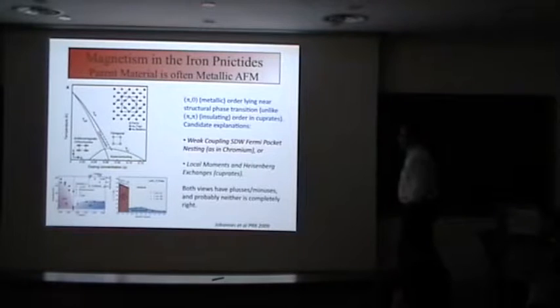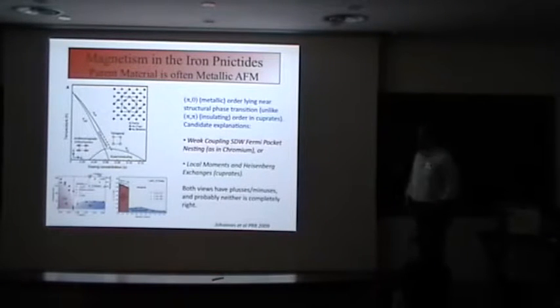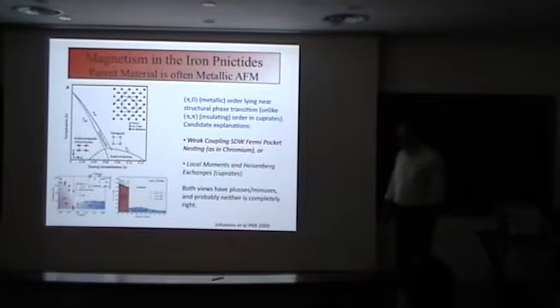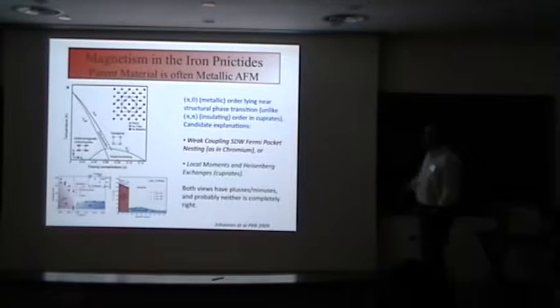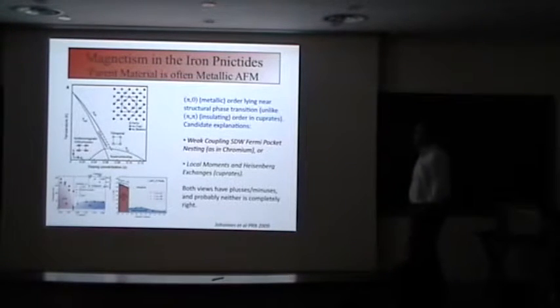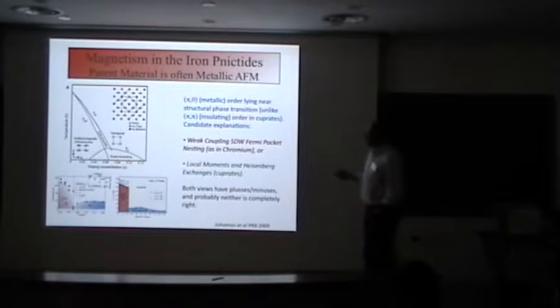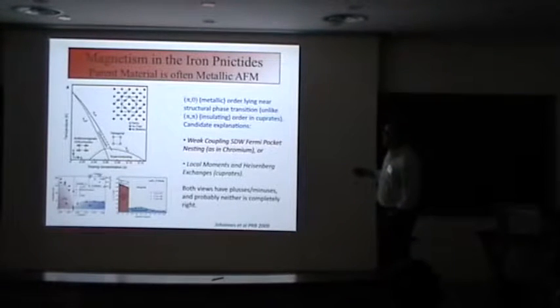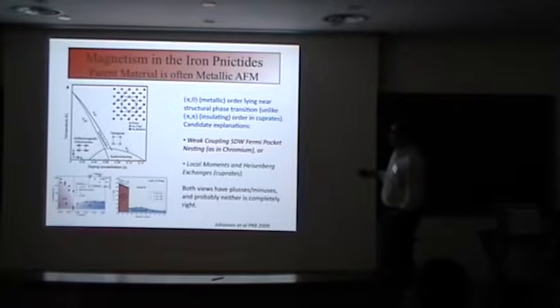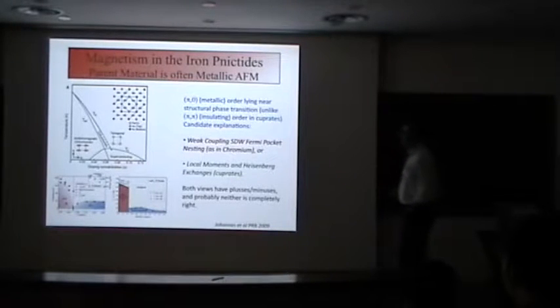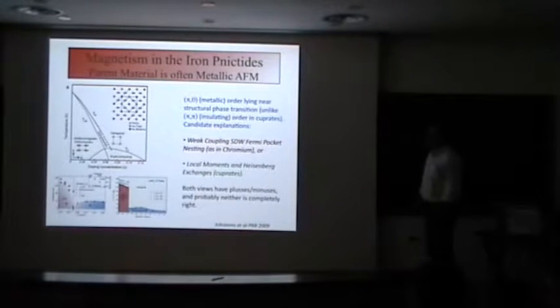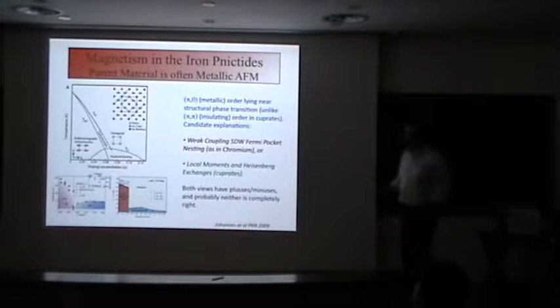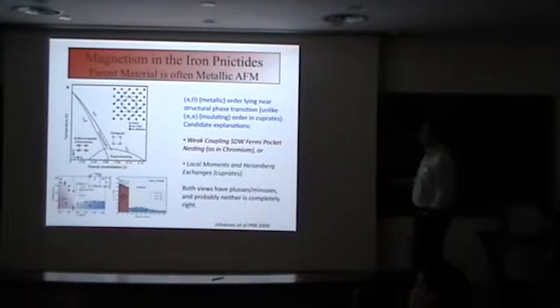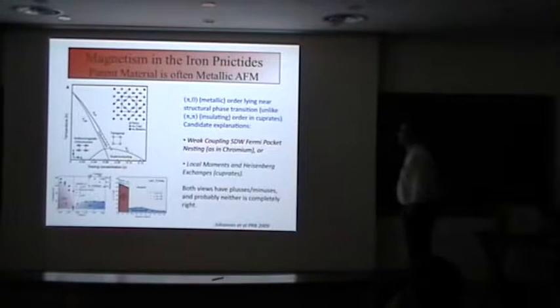And the order that appears is not like in the cuprates in terms of a checkerboard pattern formed of localized spins being an insulator, but is a metallic spin density wave state, which forms this collinear pattern of spins aligned along a particular direction and anti-parallel with another. So looking at the one iron unit cell, which is always the way I like to think about things, it's a pi-zero type of ordering.